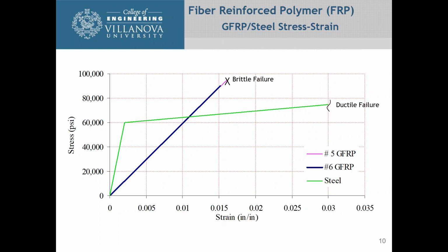Just to give you an idea of what type of failure you get, the green line is a normal reinforcing bar. You can see the stress strain curve goes up to 60 KSI, and then you get elongation due to yielding of the reinforcing bar, and you end up with eventually a ductile failure. The stress strain curve for a GFRP bar has a lower slope, so it has a lower modulus of elasticity, and you can see that it breaks brittly. There is no elongation. So with this type of material, you have to design everything differently than you would with steel. You have to design it so the concrete fails before the GFRP bar does.